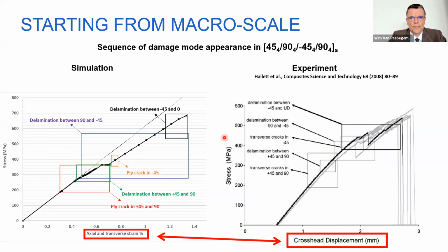If we apply this now, here you see a validation experiment. The experiment is from Stephen Hollett's group on a quite specific laminate. And here you see our simulation. So we report stress versus strain. And you have here the stress versus displacement in the experiment. I don't have the time to lead you through every single detail, so you have to believe me that the sequence of damages that we see here in our simulation corresponds very well with the observed sequence in Stephen Hollett's experiment. But you also see that here you have these drops, and we don't have them here. So that is because strain and displacement are obviously not the same.